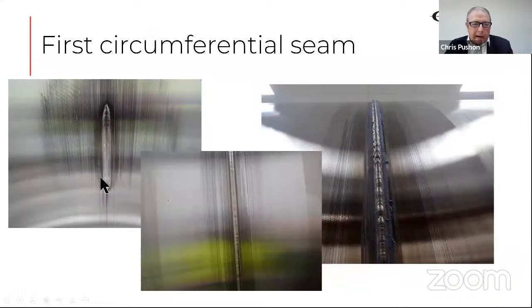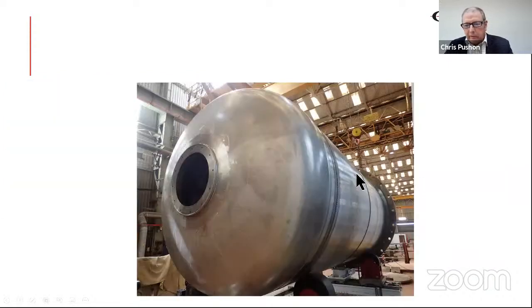And so what you see is we carried out a local tack weld, a continuous tack weld, and then a continuous circumferential weld. And the end result is a fully welded and inspected pressure vessel produced in minimal time in a shipyard where the roof leaked, and there were a lot of pigeons, and the combination of pigeons and rain coming through the roof made it quite an interesting environment during lockdown.